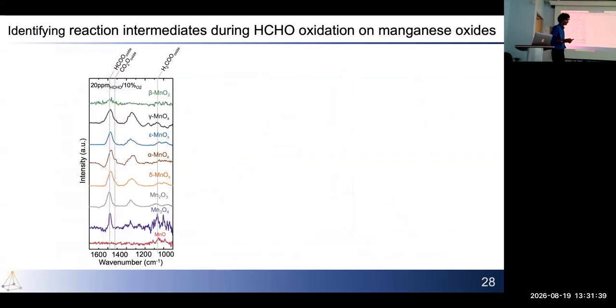Similar to the experiments I showed earlier about adsorption of formaldehyde and figuring out what reaction intermediates form on the surface, we ran the same experiments for this whole library of compounds.